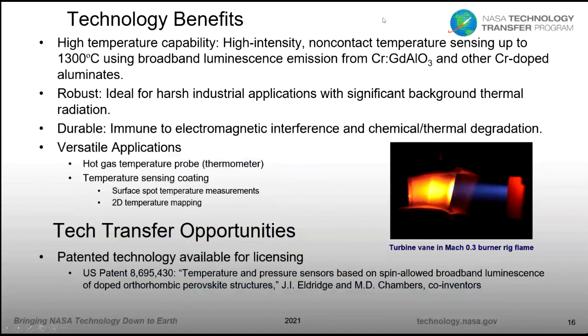Let me now summarize the technology benefits using this approach. First of all, it has high temperature capability, and because of the high intensity of the emission, that allows you to perform non-contact temperature sensing up to 1300 degrees C using the broadband luminescence emission from chromium-gadolinium aluminate and other chromium-doped aluminates. These measurements are robust. They're ideal for harsh industrial applications with significant background thermal radiation. They're durable. The measurements are immune to electromagnetic interference and chemical and thermal degradation.